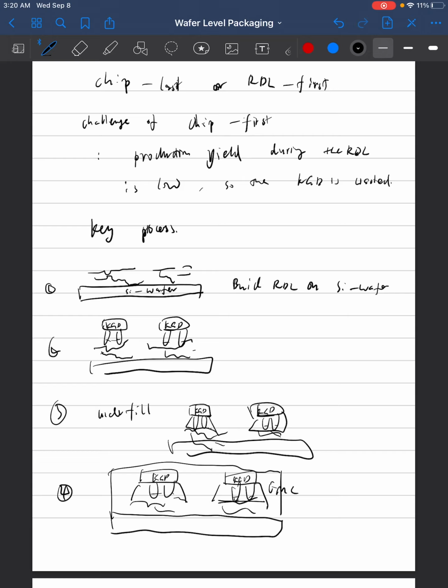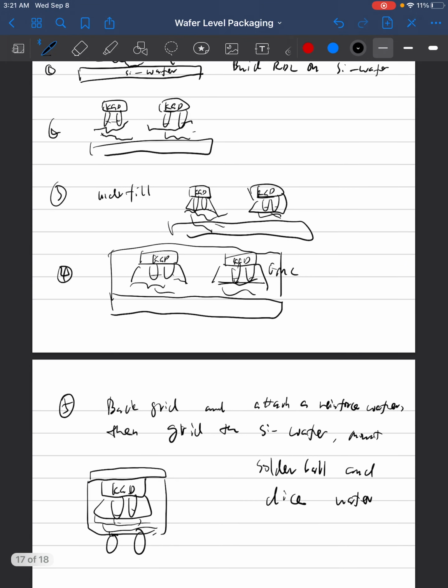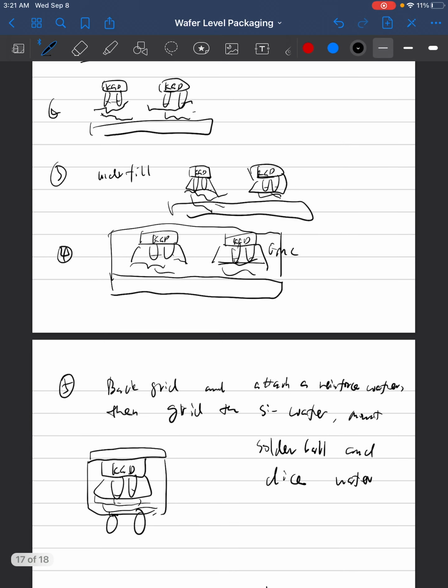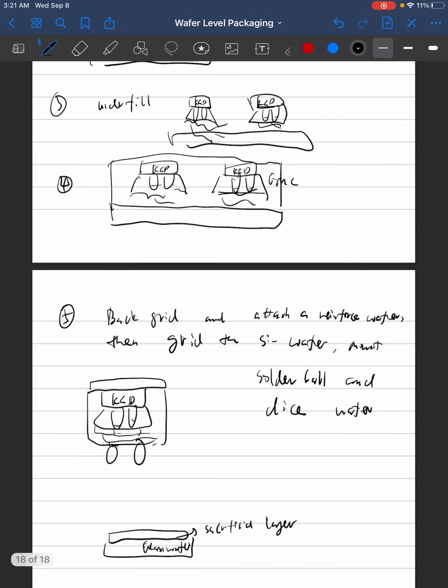After that, we can attach the known good dies facing down on the RDL layers. Then we can have the underfills and add the EMC, epoxy molding compound, onto that for protection. Then we can back grind the additional EMC, then attach the reinforced wafer onto the known good die. Then we can grind the silicon wafer, or use the laser debonding technique to remove the bottom wafer if we use a glass carrier wafer with sacrificial layers. Then after that we can mount the solder ball and dice the wafer. So that's the standard process.